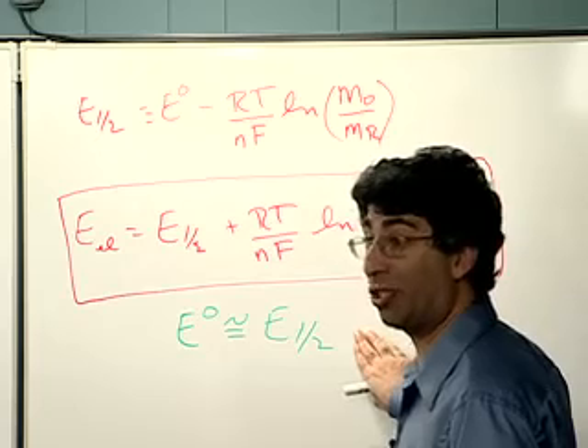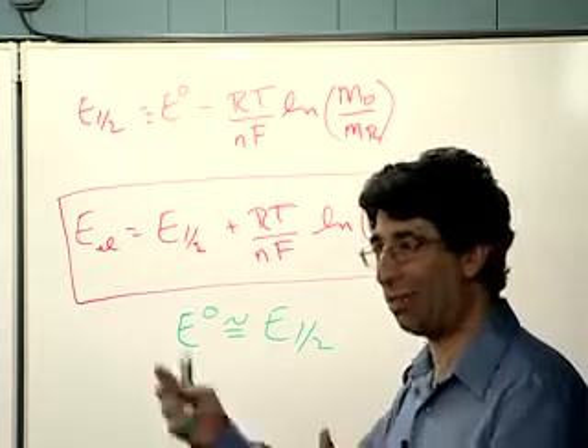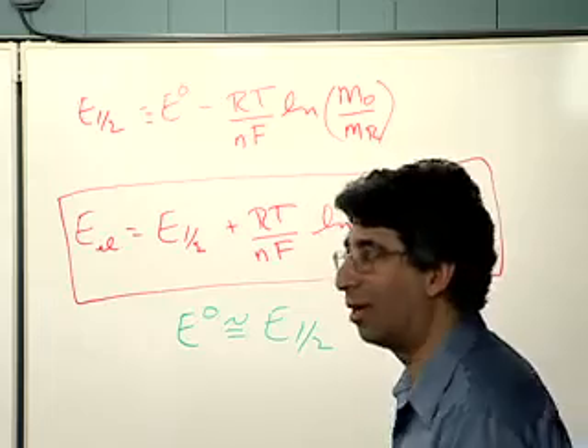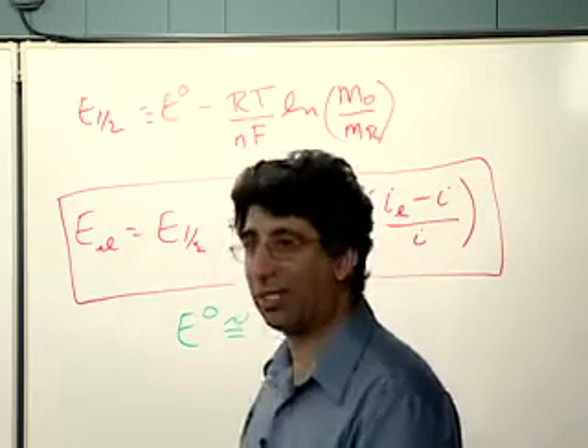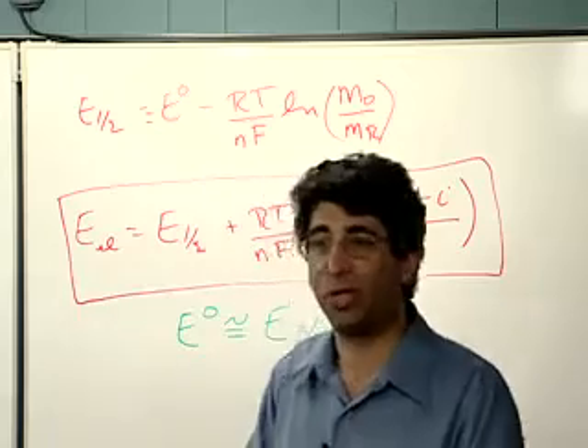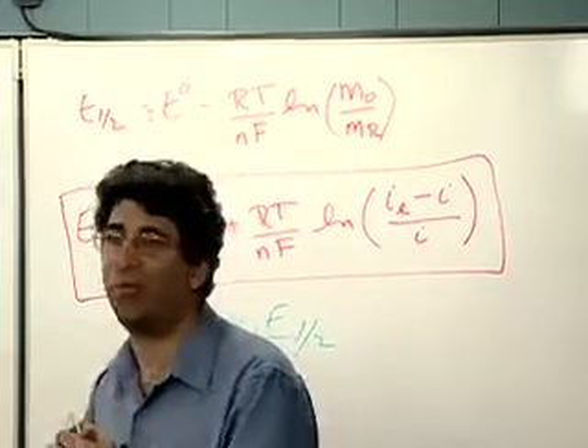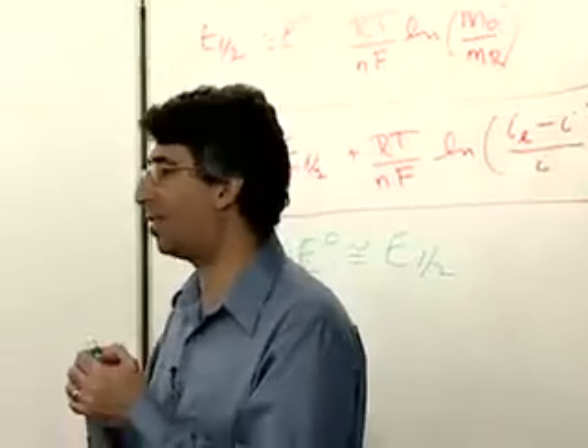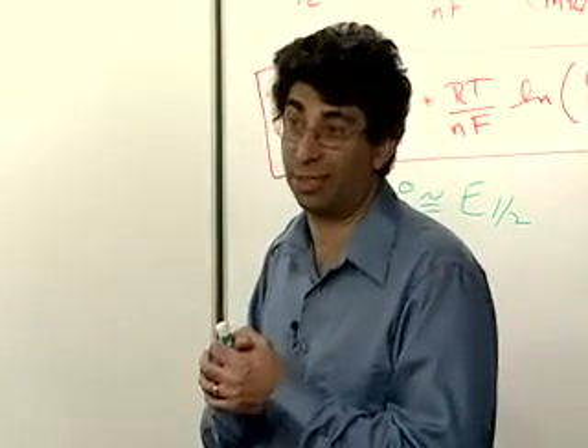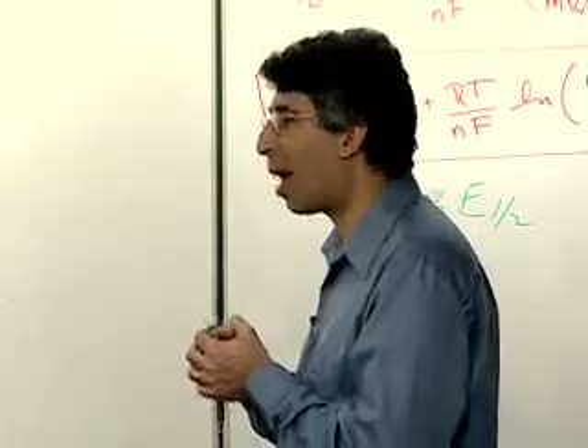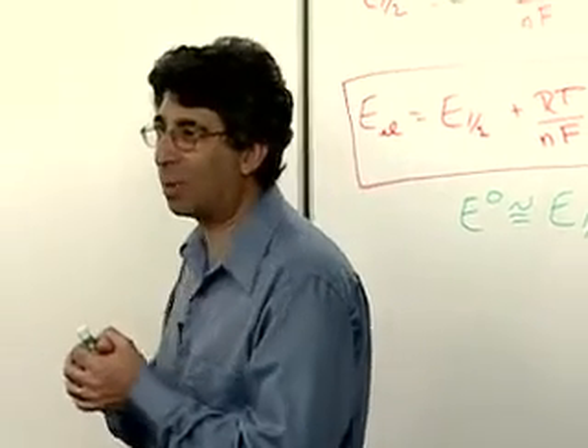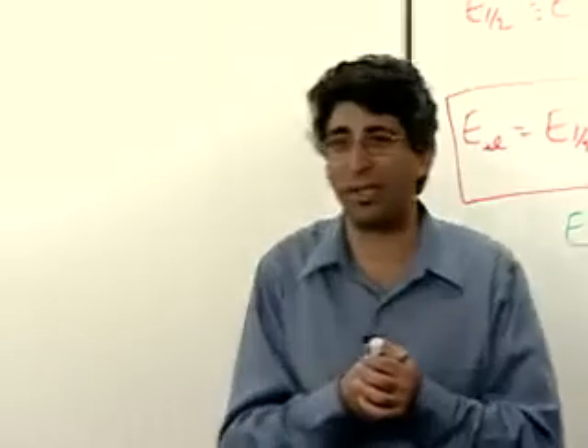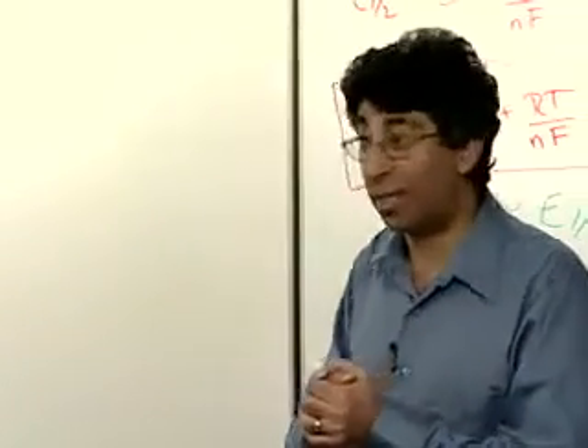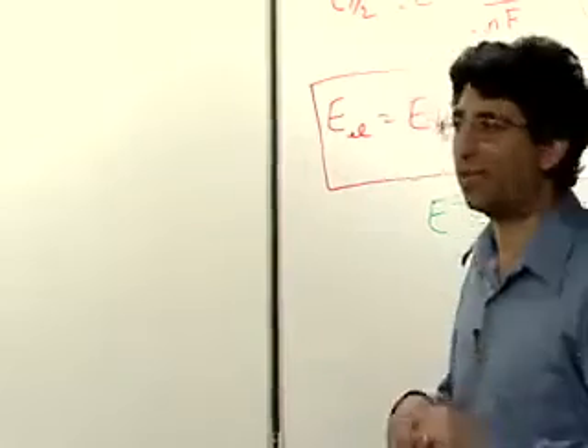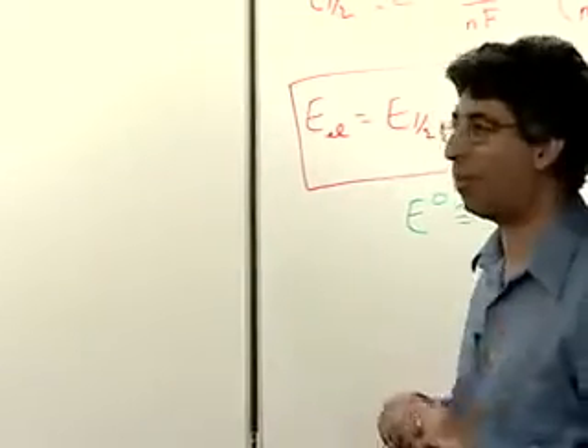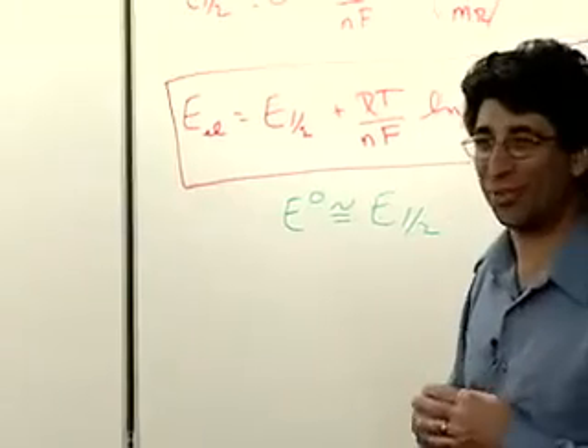Because, again, the molecule has changed dramatically between the oxidized state and the reduced state, and it's not diffusing through this. To get a feeling for this, a typical number for a molecule diffusing through solution, for the diffusion coefficient D, would be on the order of 10 to the minus 5 centimeters squared per second. If you're walking down Colorado Boulevard and someone walks up to you and says, "What's the diffusion coefficient for ferrocene in acetonitrile?" and you have no idea what the answer is, just say, "Oh, it's about 10 to the minus 5 centimeters squared per second," and they won't bother you anymore. It's a good number for things in solution, okay?